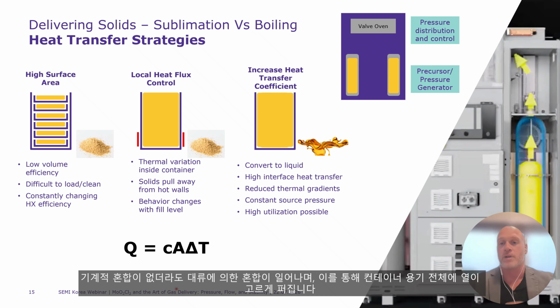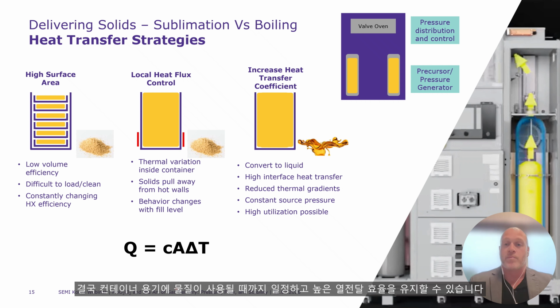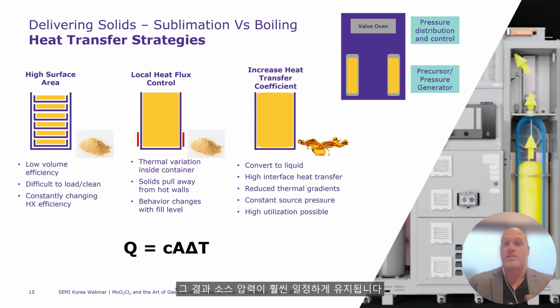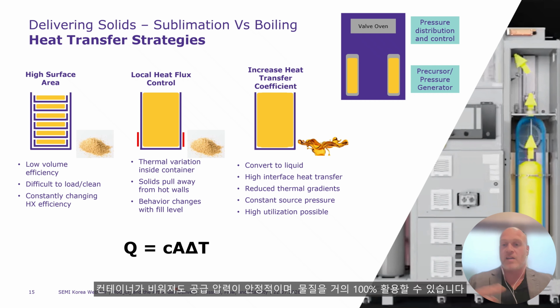Even in the absence of mechanical mixing, you're going to get convective mixing that distributes heat throughout the container. And so this ultimately means you have pretty consistent, high interface heat transfer throughout the whole duration of the container. You have reduced thermal gradients because the liquid and materials are moving around, and that heat transfer is good. You're going to have a more constant source pressure. So even as you deplete, because that heat transfer is good, you're going to have good delivery pressure. And then you're really able to utilize almost every molecule within that. So these are various different strategies that you can take when considering delivery of different solids.